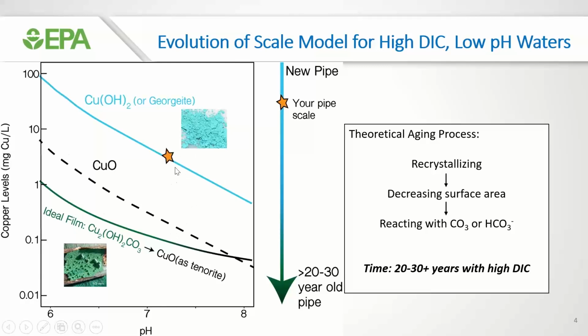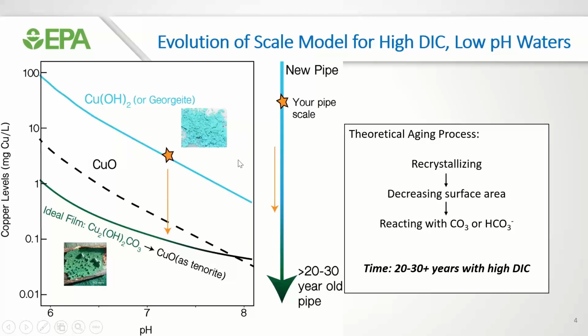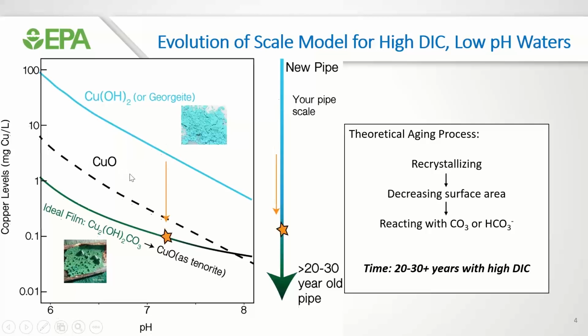So I've got copper plotted here against pH. And what happens is that with time, you start out with this new pipe, but with time, copper levels come down as the minerals on the surface, as the georgeite or cupric hydroxide age with time. They recrystallize, there's surface area changes, they react with water chemistry to eventually form either tenorite, which is CuO, a black material, or malachite, which is the copper hydroxycarbonate mineral, depending on the pH. So as you can see, the solubility is quite a bit lower. So aging is really important. And this can take decades, 20 to 30 years or more for this aging process to take place. So that's really the key.